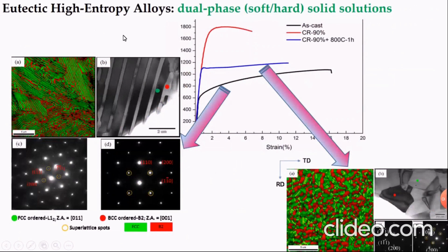In another research, a eutectic high entropy alloy with dual phase, soft and hard solid solution. We have both of the structures. We have FCC and we have BCC. The green one is FCC and the red one is BCC. But it's an ordered BCC, it's called B2 actually. If we see here, we have interchanging phases, one soft and one hard, which is very good for different applications, like load bearing applications, wear resistance, and so on.